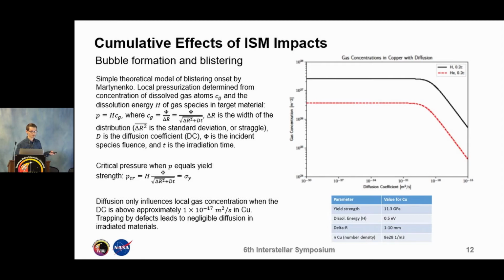Now, there are two expressions for the gas concentration. One is just phi over delta R, where you don't take into account diffusion in the material. If you'd like to include diffusion, you can include this extra term in the denominator in the radical, where D is the diffusion coefficient and T is the irradiation time. However, it is often assumed that irradiation damage produces enough defects in the material that the defects can serve as trapping sites, and thus the diffusion coefficient can become negligible.